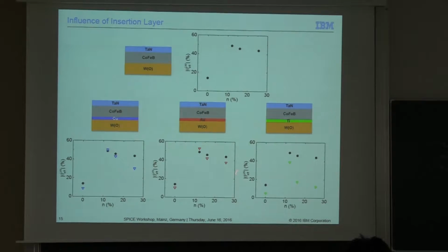If my spin Hall angle is completely due to a bulk effect and not an interface effect, the experimental data I measure should lie exactly where these open symbols are. The black symbols are when there was no insertion layer placed in between. Experimentally, when I measure this, I see that it is very significantly different. And this is what proves that this is an interface effect.